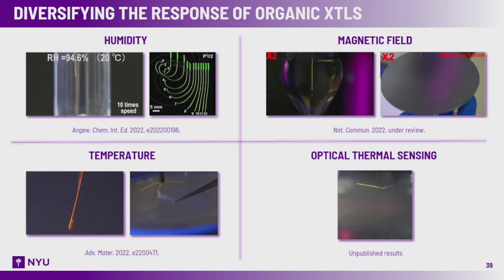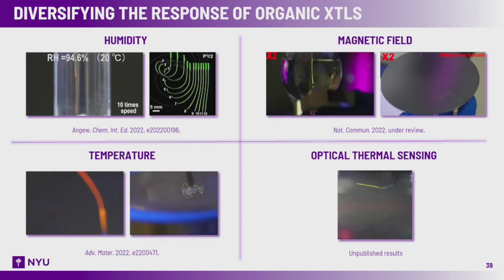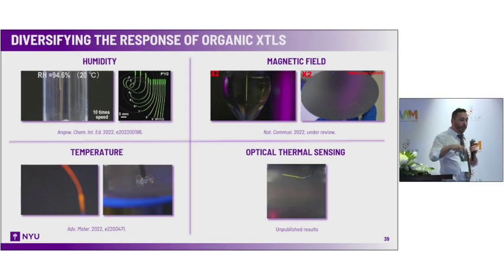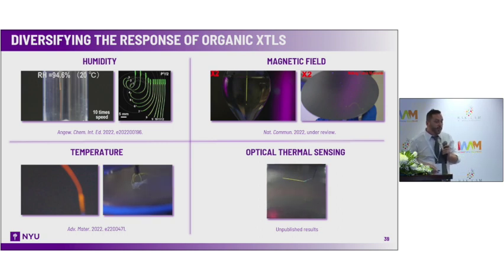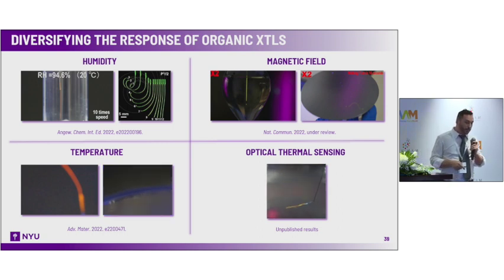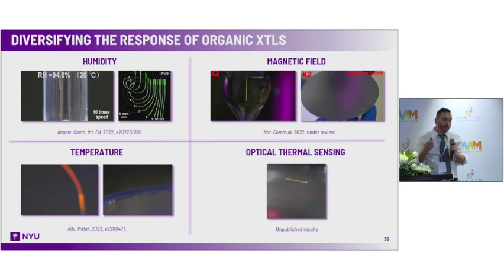In another example, we use the temperature, and this is a very, very fast transformation, as you can see. But you can also think about making small soft robots or grippers, where when they cool down, they curl, and they take objects and transfer the objects from one place to another. And also, we can think about optical thermal sensing applications. So all kinds of research are going on. Again, in this case, we use the elasticity of the crystal, but we add value by coupling this with polymers, which bear a range of functionalities. And this hybrid approach actually gives us a lot of opportunities to play with.